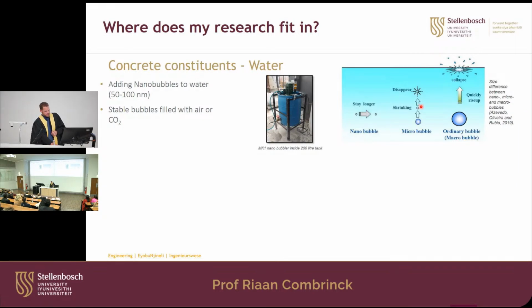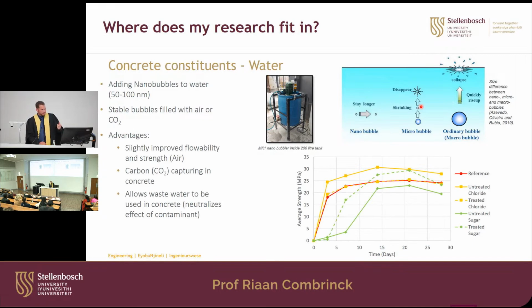Some of the advantages we've been seeing are slightly improved flowability and strength with air. We're still working on it. I think we can get higher strengths, but that's what research is about. Then a very promising one is that we're actually incorporating CO2 bubbles into the concrete. That is a way of capturing the CO2 in the concrete, getting rid of the problem directly by putting a high quantity of CO2 in the concrete.